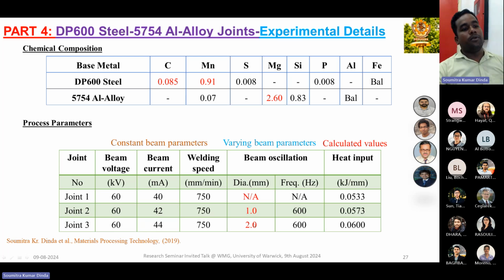But this parameter, 1 millimeter to 2 millimeter, the beam diameter plays an important role for microstructure and also mechanical properties. And here we also increased the beam current a little bit, but very negligibly, within 1 or 2%, to get proper 100% full penetration. And again we calculate the heat input. So here if we compare amongst joints 1, 2, 3, joint 1 is without oscillation, joint 2 is the 1 millimeter oscillation diameter, joint 3 is the 2 millimeter oscillation diameter.